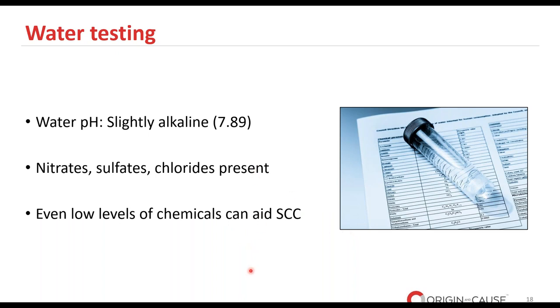Now let's transition our attention to the water component. As I mentioned, we conducted a thorough testing of the water to identify its potential contributions to the faucet's degradation. An observation was that the water's pH level stood a little high at 7.89, so it was alkaline. And an alkaline environment can impact metal behavior and its interaction with the surrounding elements.